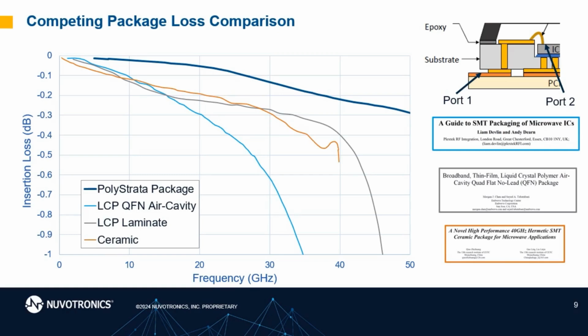So the dark blue line is plotting the PolyStrata QFN package performance, and you can see across the frequency band, even down below 20 gigahertz, our technology offers lower loss, and that loss improvement becomes even more dramatic as we move higher in frequency above 40 gigahertz. And this is because of our unique transmission line being coaxial, and the ability to tune the entire path with a lot of flexibility.